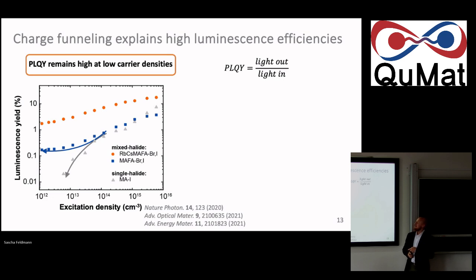But interestingly, for all these mixed halide compositions, and I show here two in blue and orange, but really we looked through a whole zoo of different materials, all that have a mixed halide bromide iodide case with this heterogeneous energy landscape, they all level out at rather nicely high efficiencies, even for the very lowest of excitation densities. Now that's very useful, because if you think about it, you do not want your solar panel to only operate perfectly well under sunny conditions. It should do a good job under the conditions right now, cloudy, perhaps below one sun. This is kind of below here.